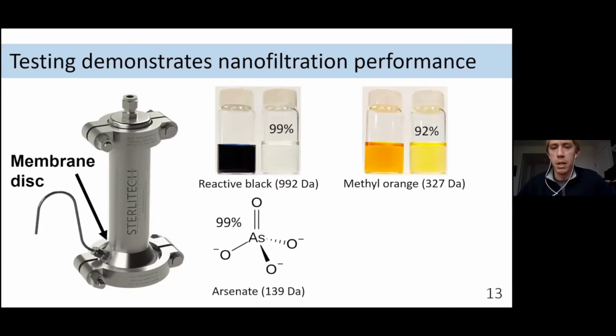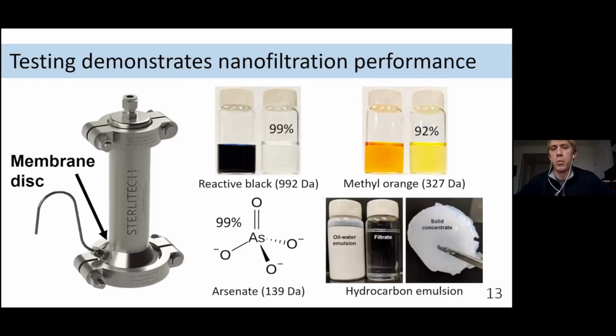The smallest thing we've done is with arsenate, and that's obviously a big problem in places like Southeast Asia in terms of groundwater contamination. About 100 million people there are currently suffering from exposure to arsenic. We're able to remove upwards of about 99% of that from the feed stream, and this is working us down towards divalent salt type of rejection. Also important is not only the size of what you're rejecting, but also the chemical character.